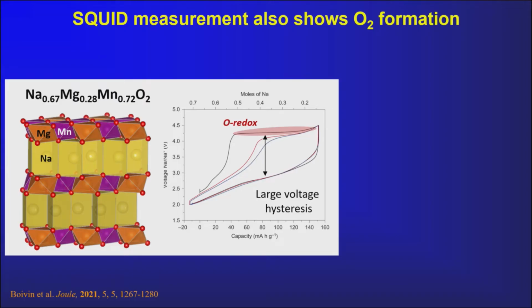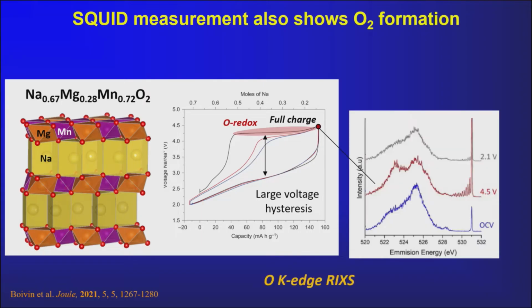You still get oxygen redox in this material. There's the plateau and the hysteresis again. I'll show you why in a moment. But the important thing is you do get oxygen redox, and this is just a line spectrum from RIXS, not the map this time. And this feature here is the feature that is the signature for molecular O2.